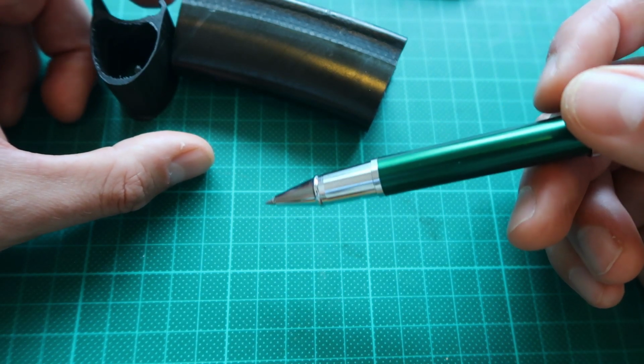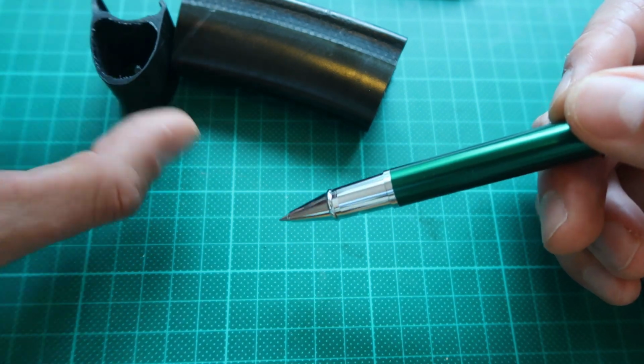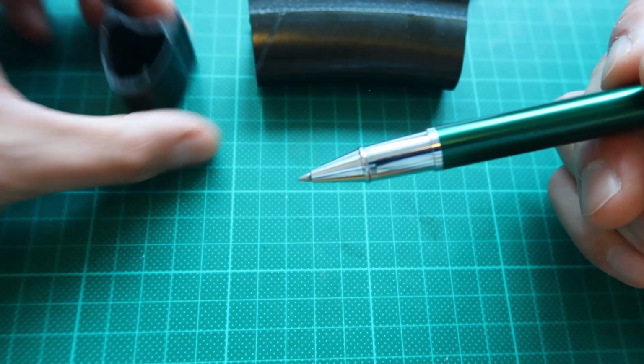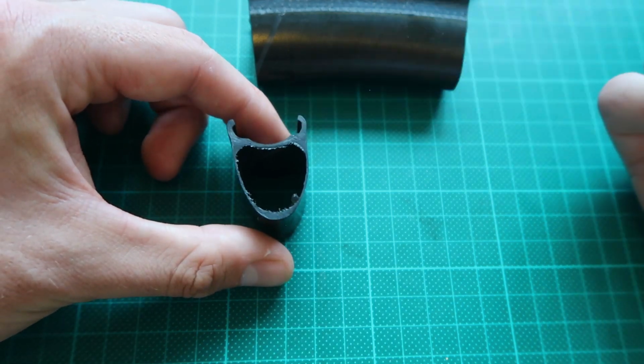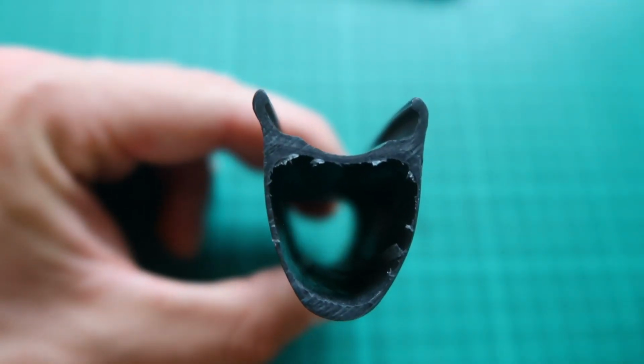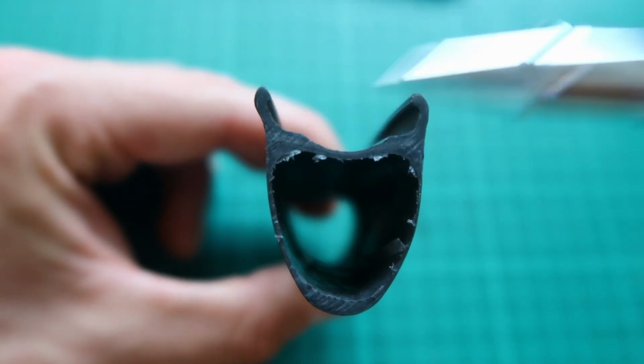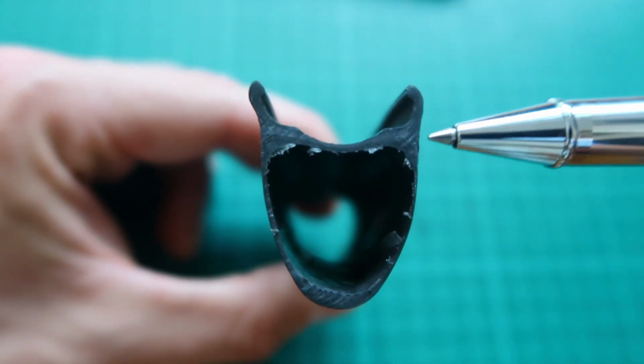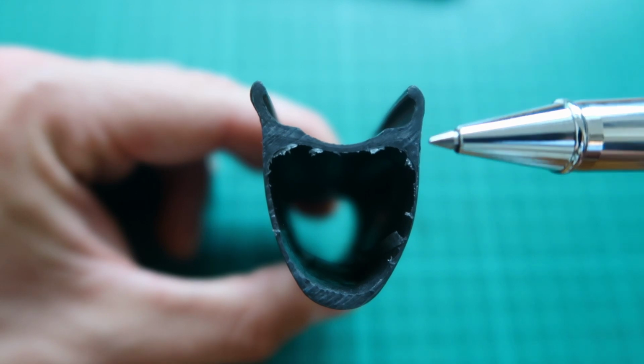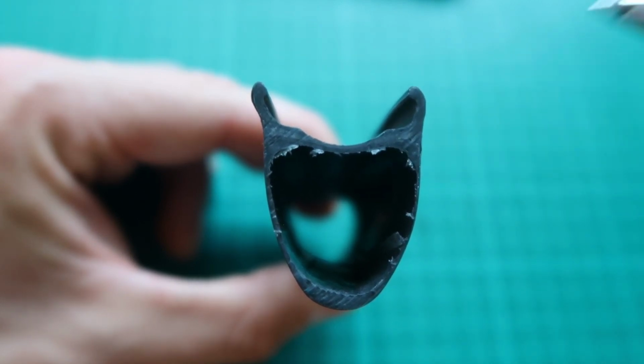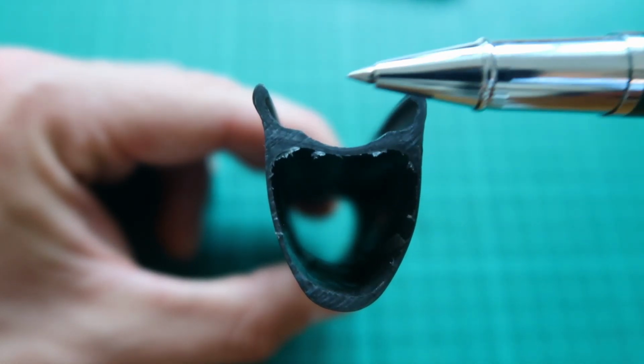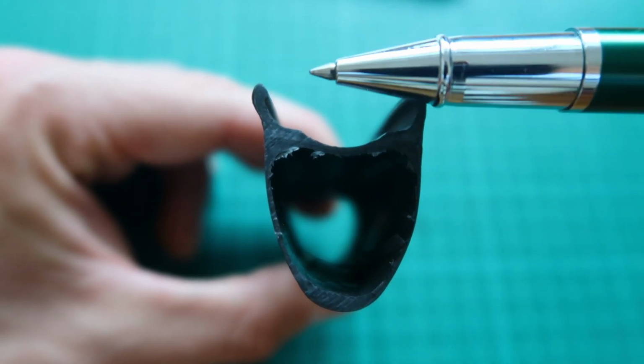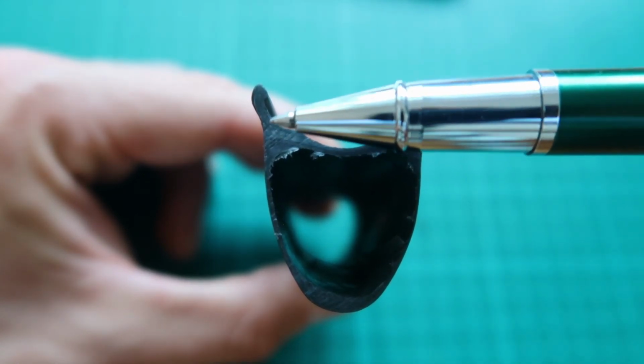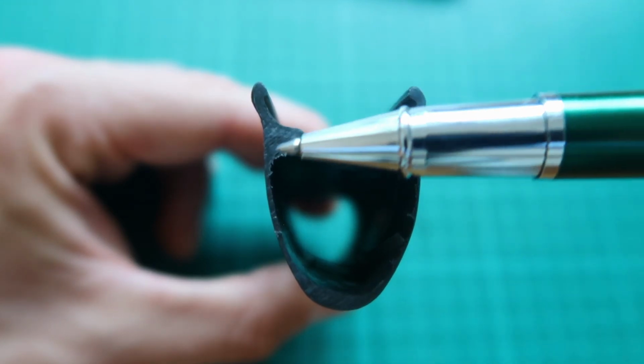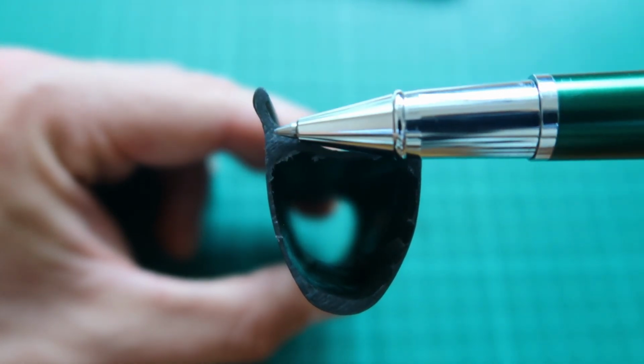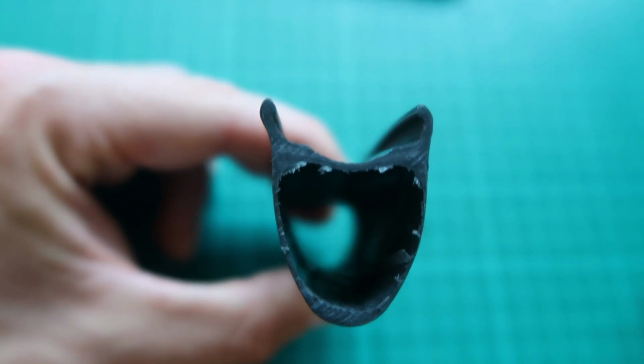So I carried on cutting it, cut it in a few places where the warping was the worst on the sidewall by the brake track. This is probably the worst bit of the rim that's warped, and you can see basically what's happened is the epoxy in the pre-preg has got too hot. It's gone towards the glass transition temperature, and we'll talk what that is in a minute, and the pressure from the tyre has exerted a side load on the sidewall, and it's just bulged out the brake track, where the epoxy here locally has got very soft because of the heat build-up.